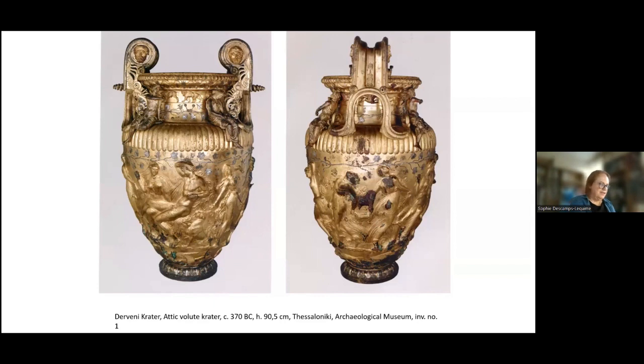And on the right, on the fourth step, you have 15% tin, and this is the composition of this exceptional masterpiece, which is kept in the Archaeological Museum of Thessaloniki. And it's such work, as Beryl Barr-Sharrar proposed and showed, it was probably made in Athens around 370 BC, and it is very, very high, more than 90 centimeters.